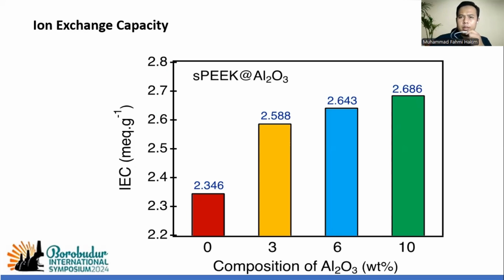Okay. This temperature was set close to 80 degrees Celsius, because the membrane may become unstable beyond this temperature. The ion exchange capacity of 3, 6, and 10% sPEEK aluminum oxide was displayed in this graphic. Respectively, the increase in ion exchange capacity was due to sulfonation, during which aluminum oxide filling materials were added. Subsequently, the filling materials were sulfonated and the number of sulfonic groups in the membranes increased. The highest ion exchange capacity was obtained from the 10% sPEEK aluminum oxide membranes, and the result showed that 3, 6, and 10% sPEEK aluminum oxide are applicable to direct methanol fuel cell.